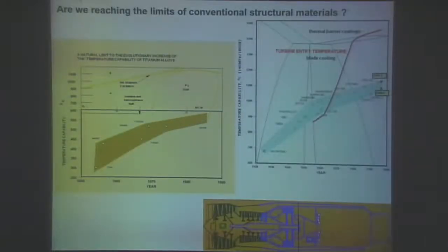But is there a limit to materials properties in aero engines? Look at titanium alloys. Somewhere around 300 degrees temperature capability, as defined by creep capability in the 1950s and 60s, to about 500 degrees today. And you're reaching the limits. You can clearly see that with every additional year, your increment in temperature capability is decreasing. And that is also true for nickel-based superalloys. And it's true for every material. As you progress with time, your ability to produce increments in performance decreases steadily.